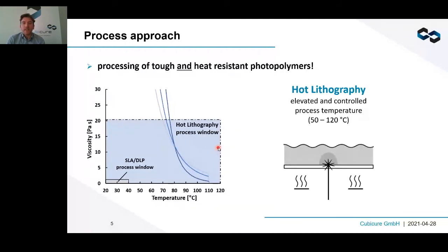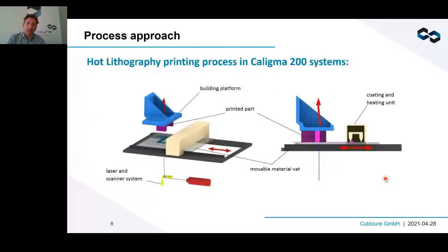And to do so, you will see that later on pictures and videos, we always use some kind of coating process to bring our viscous materials to provide them to a process zone. And we also use heat to limit the viscosity to a reasonable number. As you can see here, we use up to 120 degrees C in temperature. And at this temperature, we can process resins up to a viscosity of 20 Pascal seconds. To give you an idea, 20 Pascal seconds of viscosity, that's somewhere between honey and toothpaste. So it's already quite viscous, but our machines are able to process these viscous materials and slurries. And that's important because now with that high viscous resins, we can really generate performance polymers, which you would use for your applications.